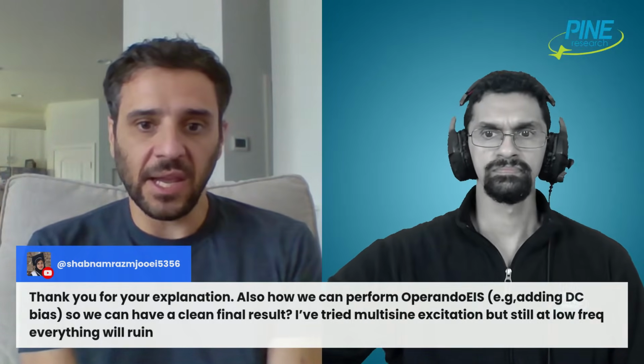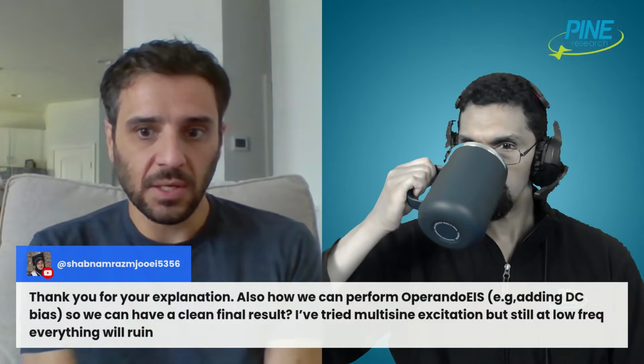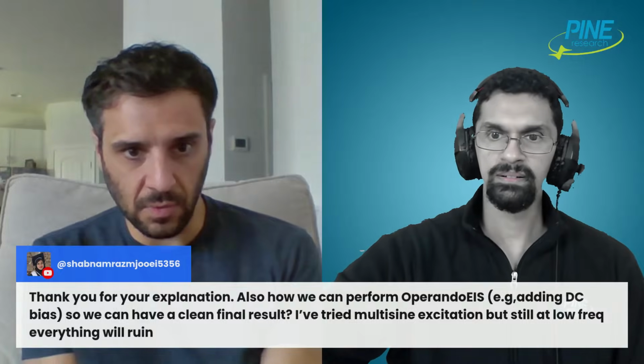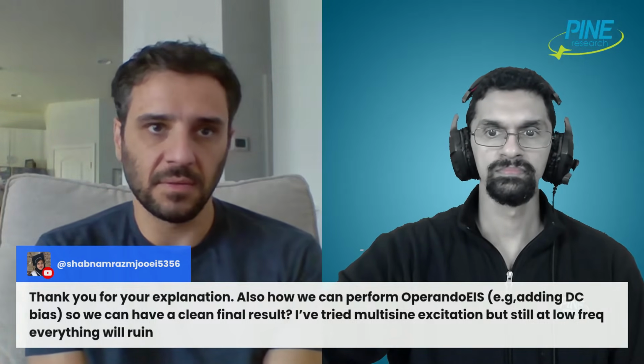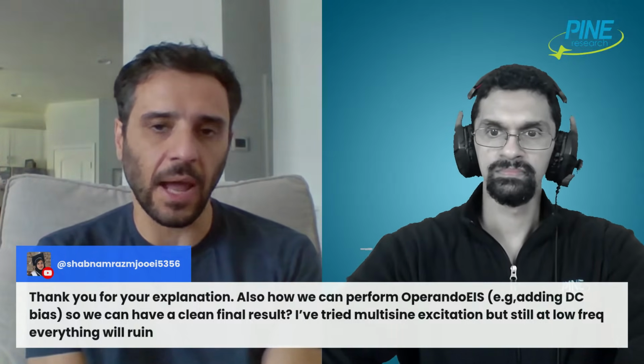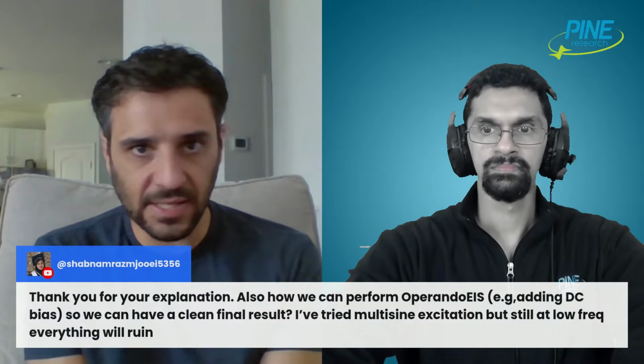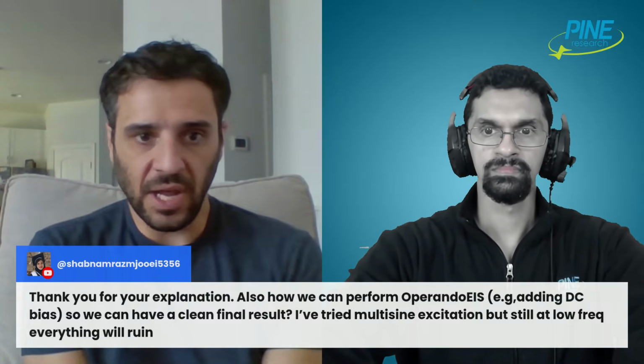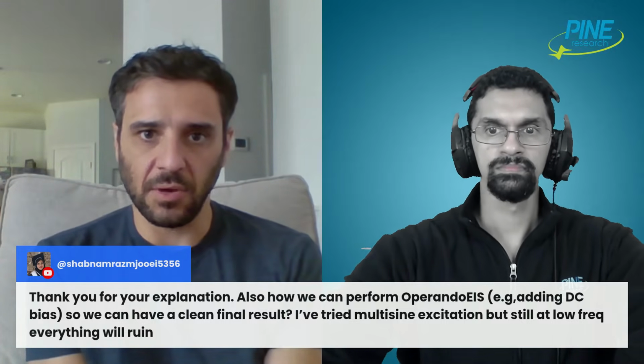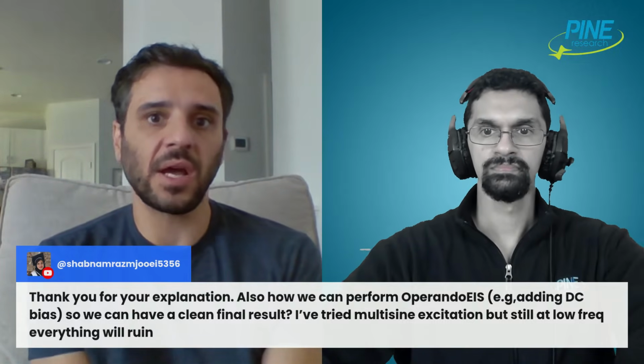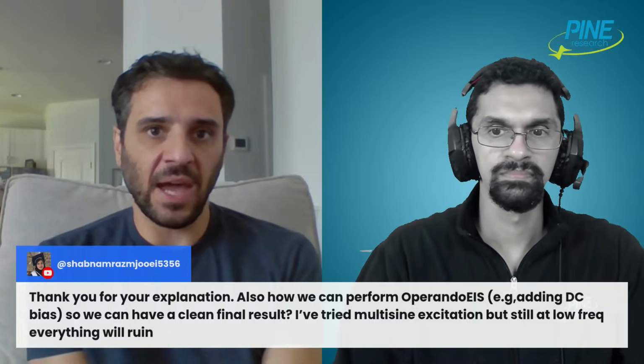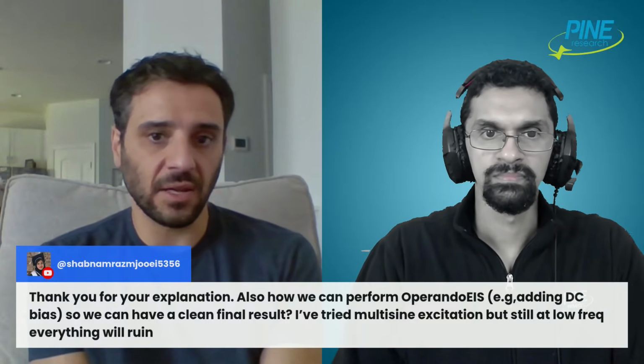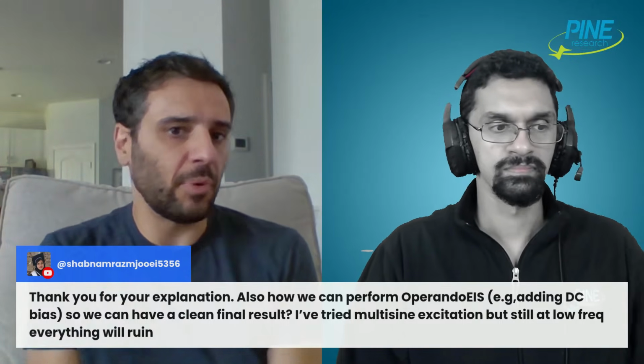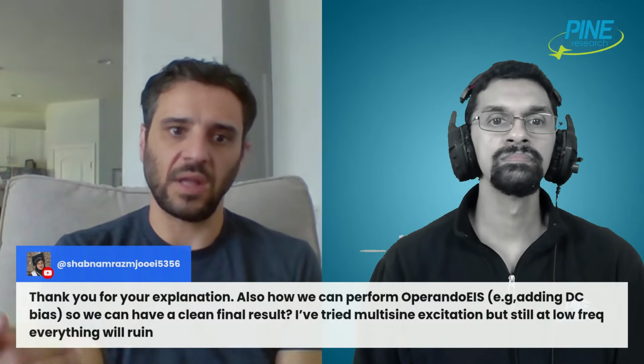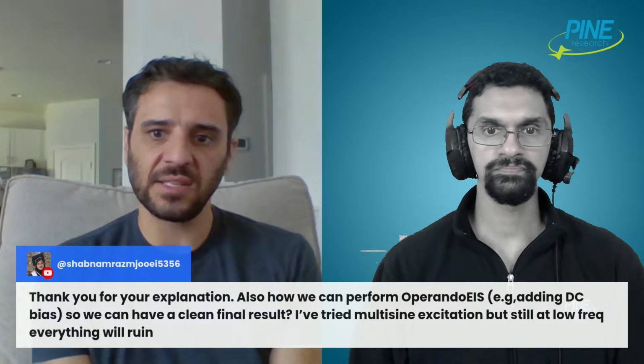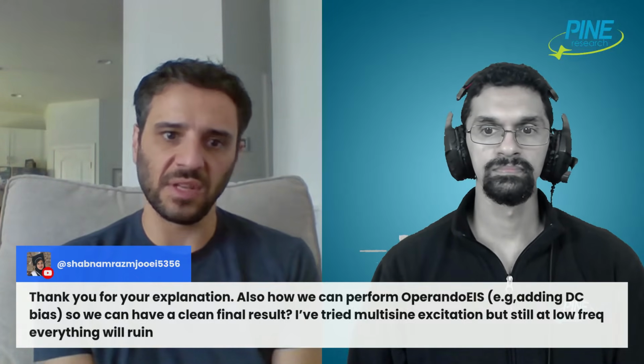So the ways to get around that are to not do low frequencies. Your question was, well, at low frequencies, it's ruined. Yeah. Because at low frequencies, it's taking a longer time. And the longer you're doing this experiment where it's already not stable and your baseline is moving, the worse your data is going to be. It's almost not possible to get good data. I did some of this kind of thing when I was a postdoc. I did impedance of batteries under load, and I limited it to, I didn't go below like 10 kilohertz, maybe 1 kilohertz, to get simple probe kinds of results under load, but quickly. And so even though it's not stable, if you do really quick tests at high frequency, you can kind of just make the assumption that it was roughly stable during that time.